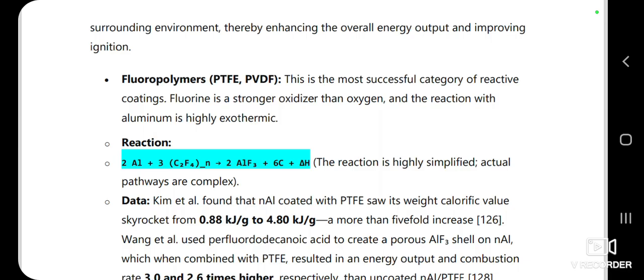Look at this reaction, that fluorine is a stronger oxidizer than oxygen, and the aluminium fluorine reaction is tremendously energetic. The data shows coating nanoaluminium with PTFE, which stands for polytetrafluoroethylene, rockets its heat output from 0.88 to 4.80 kilojoules per gram, a more than 5-fold increase.